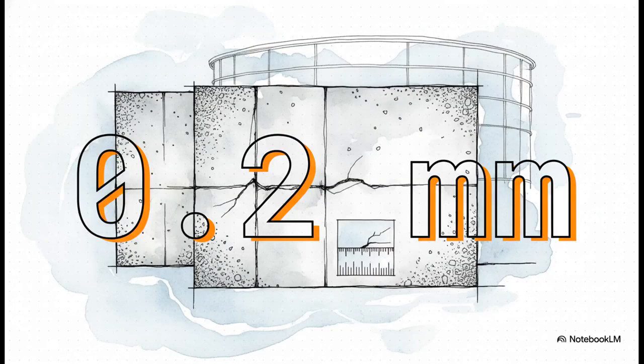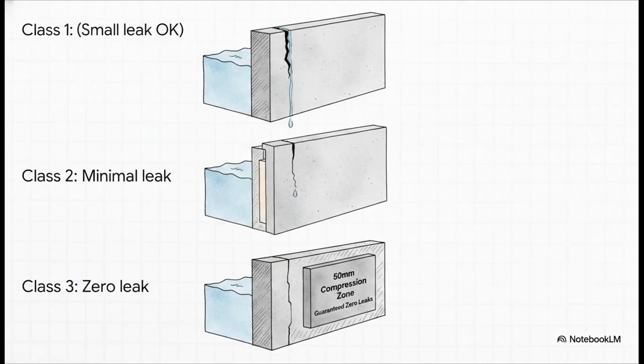Make sense? So the absolutely crucial takeaway here is this exact number, 0.2 millimeters. Listen up. Under the limit state method, for standard severe exposure conditions in a liquid retaining structure, the maximum calculated surface crack width must never, ever exceed 0.2 millimeters. Seriously, etch that number right into your brain. But it actually goes a bit deeper than that, depending on the structure's tightness class.